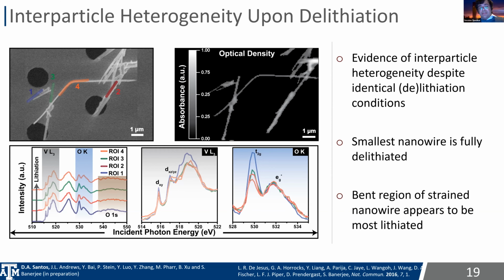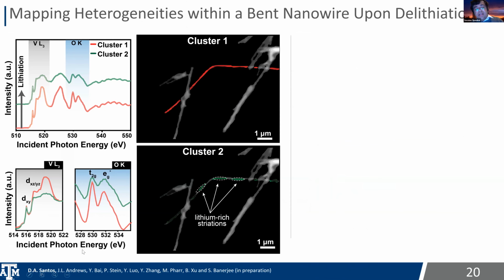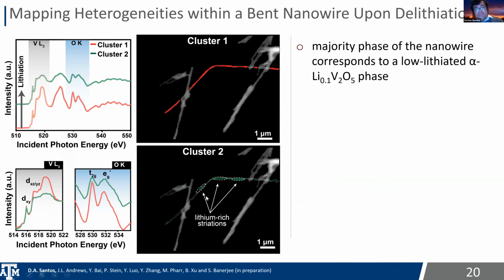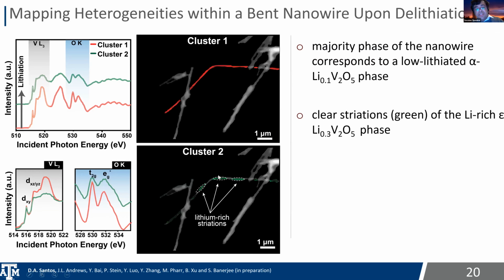Okay, and you can see here, this is a set of nanowires that have been lithiated and delithiated across several cycles. So the small nanowire is completely delithiated, but the bent part of this wire here in 4 has regions of lithium still present, really corresponding to irreversibly lithiated regions, right? And so that's capacity that has effectively been lost. And so we can dive down a little bit deeper. This is work of David Santos, using a bunch of statistical methods to identify these lithium-rich striations that actually form in these delithiated wires. So it's really, really cool.